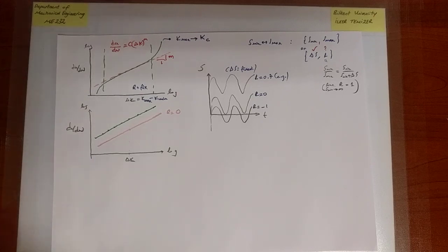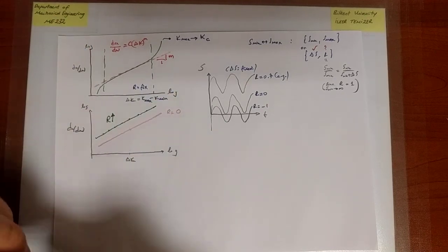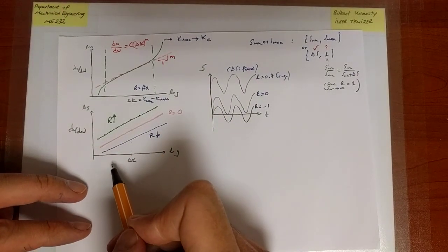And indeed, it turns out that the crack growth rate for a given delta K increases as R increases. Alternatively, if you decrease the value of R at any given delta K, you will predict a lower rate because the situation becomes less critical, and therefore the prediction of the model will shift down. Okay, so the line will shift up with increasing R, shift down with decreasing R.